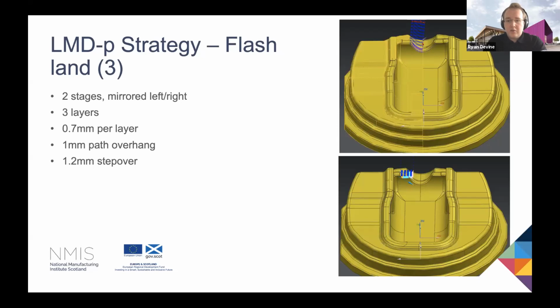Flashland 3, however, had quite complex geometry in that area. It was quite a difficult access to reach as well. So it required a bit of a unique solution for tackling it. So we split it into 2 stages, and this was mirrored left and right on each side of the radius. What we did first, and this is indicated in the top image in the slide, is we built up the incline section first. We then came in and machined that flat before then redepositing on the top, and that would then allow us to fully repair that area to a satisfactory quality.